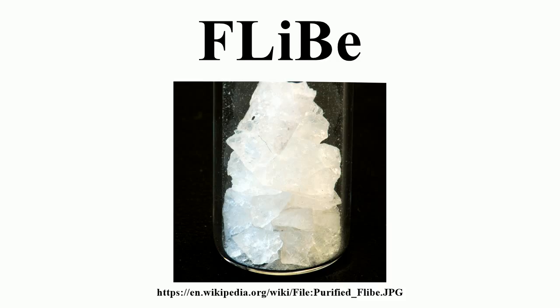Nuclear properties. The low atomic weight of lithium, beryllium, and to a lesser extent fluorine make FLiBe an effective neutron moderator. Natural lithium contains 7.5% lithium-6, which tends to absorb neutrons, producing alpha particles and tritium. Nearly pure lithium-7 is used to give the FLiBe a small cross-section, e.g., the MSRE secondary coolant was 99.993% lithium-7 FLiBe. Beryllium will occasionally disintegrate into 2 alpha particles and 2 neutrons when hit by a fast neutron.